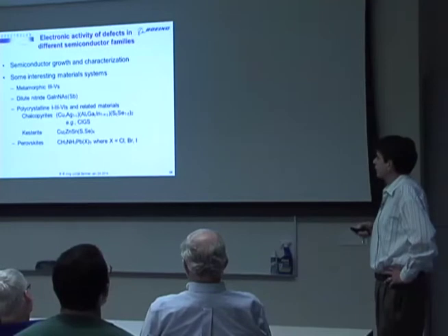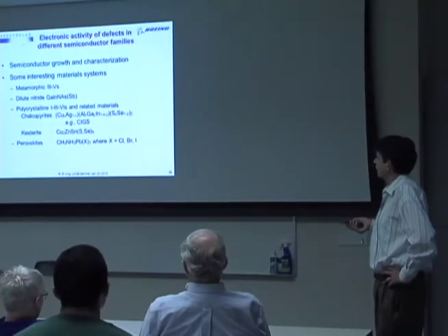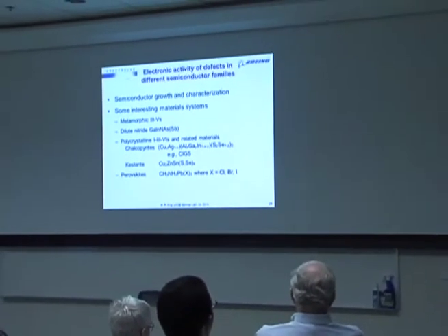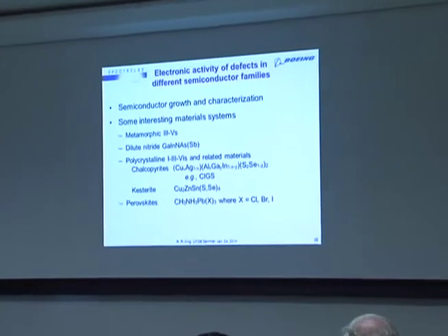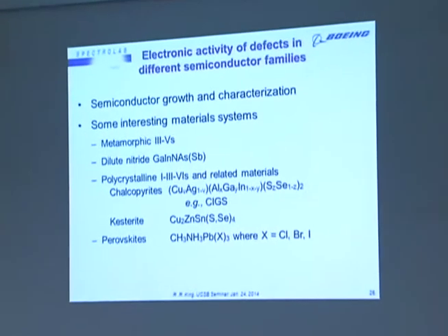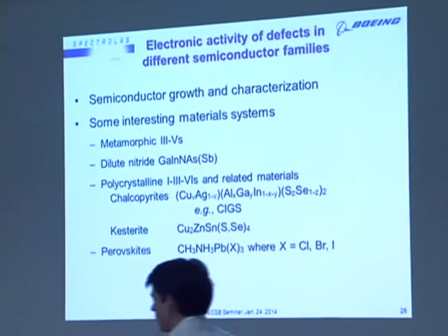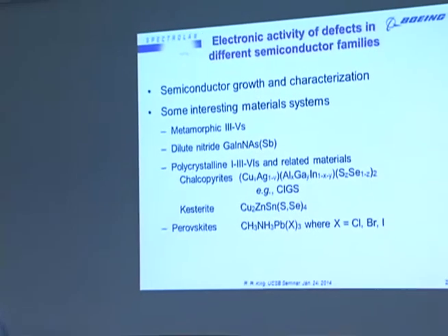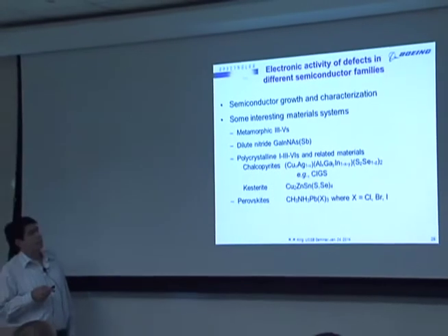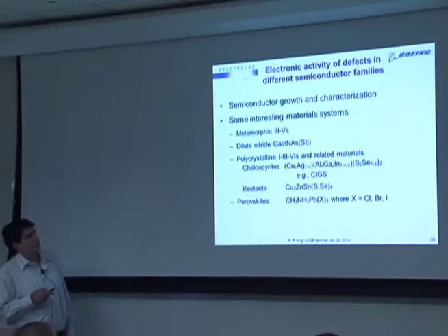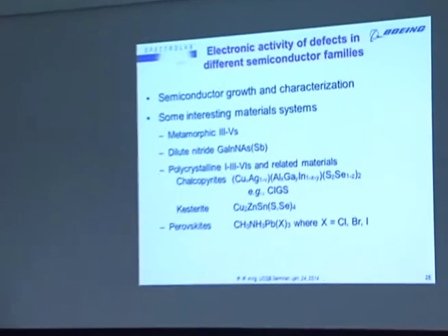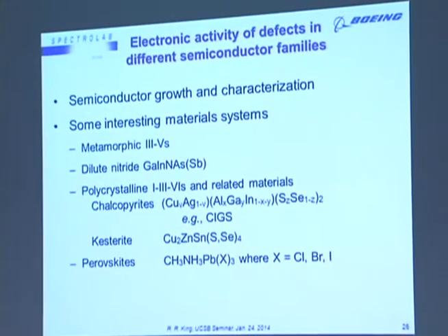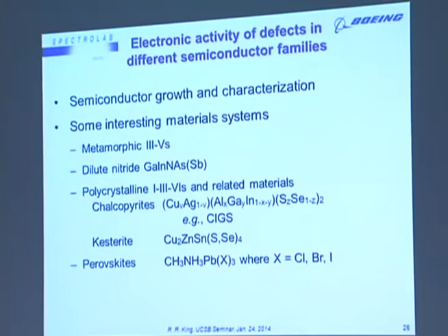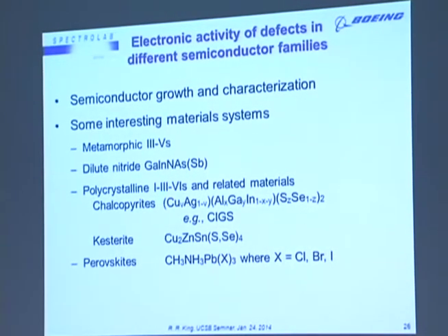Very important is how you grow these materials, of course, and the defects that are introduced by the growth process. Some of the more interesting material systems that we've worked on at Spectrolab for their ability to tune the band gap of subcells to form a better match to the solar spectrum in multijunction cells are these metamorphic III-Vs, or lattice mismatch III-Vs, dilute nitride gallium indium nitride arsenide, which can include antimony in the composition, and polycrystalline I-III-VI and related materials.